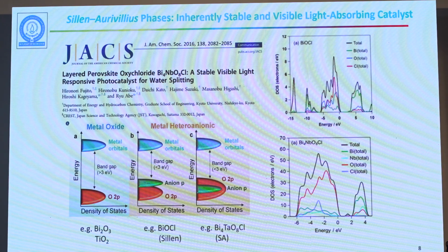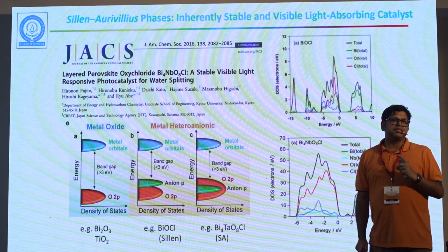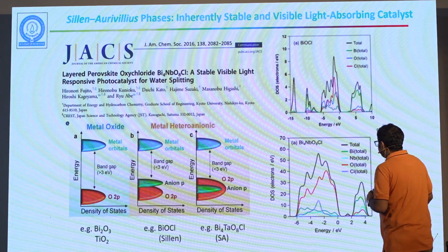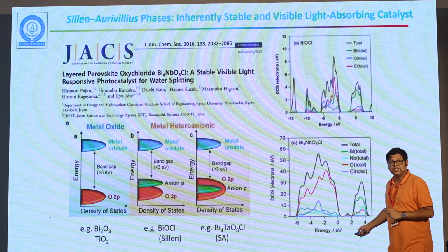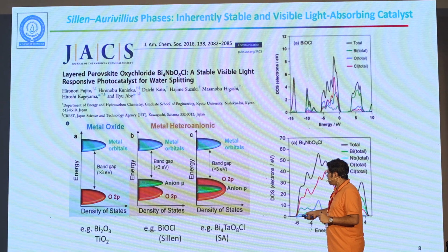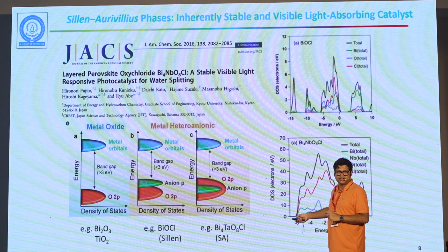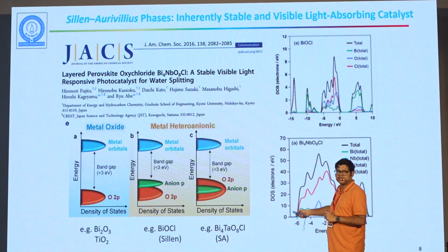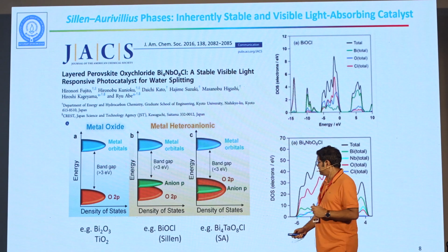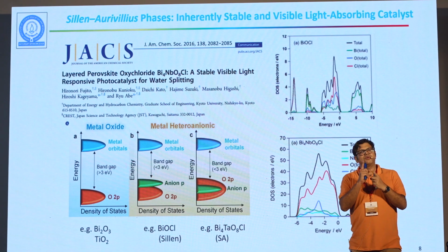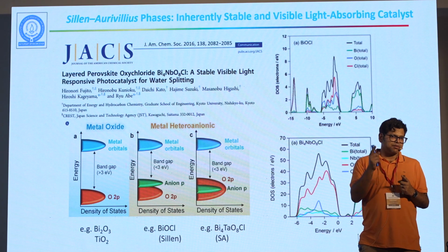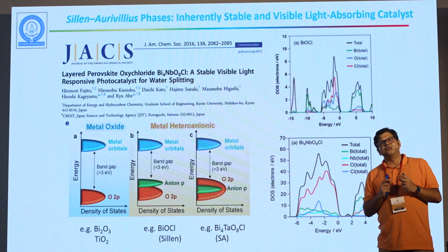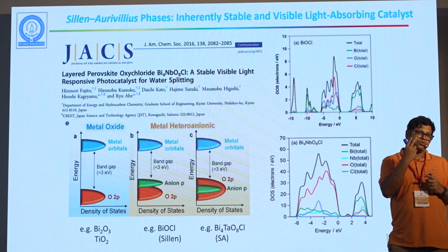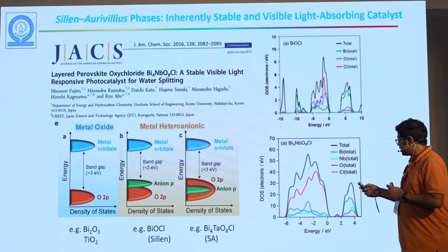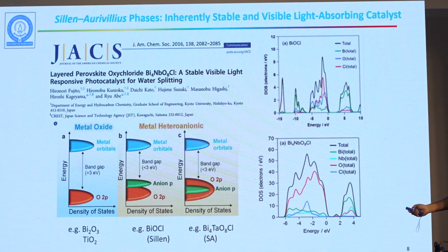Now what happens, if you take the Sillen phase, only BiOCl phase, this is a very good photocatalyst. But its stability is not good. And the reason is the following. If you look at this band structure, okay? You have oxygen and we have chlorine on the valence band, and we have metals in the conduction band. Now, when these electrons get excited, it gets excited from chlorine. So if chloride gives one electron to the metal, it becomes chlorine and it comes out very easily. Which is difficult in case of oxygen because oxygen has to give 2 electrons. Chlorine has to give only 1 electron. So instead of chlorine, if you have oxygen here, this will be much more stable.